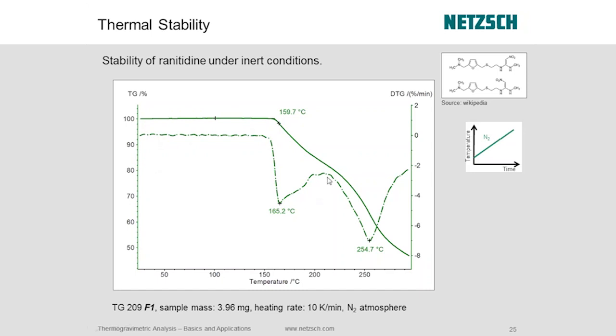And then also, this is where we break for that onset. But here in the derivative, we can see the maximum point here would be around 165, and then the maximum point in that second step around 255 degrees C. Okay? So that tells us about thermal stability of this pharmaceutical material in inert atmosphere.